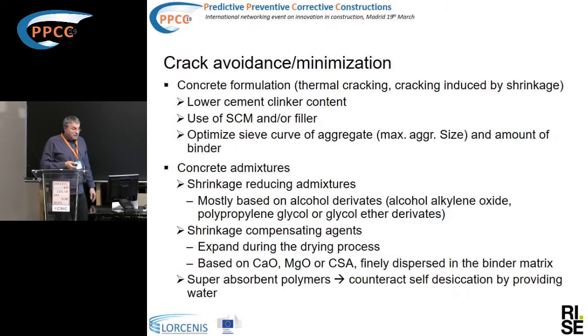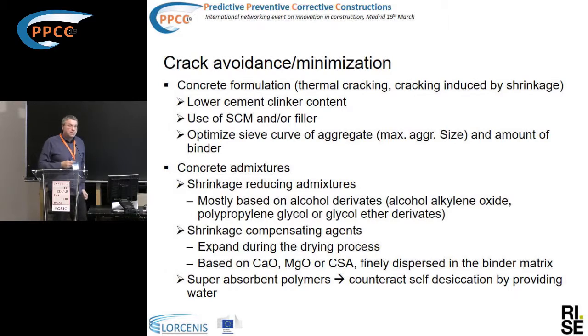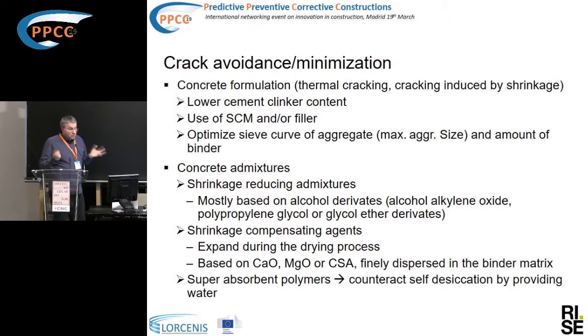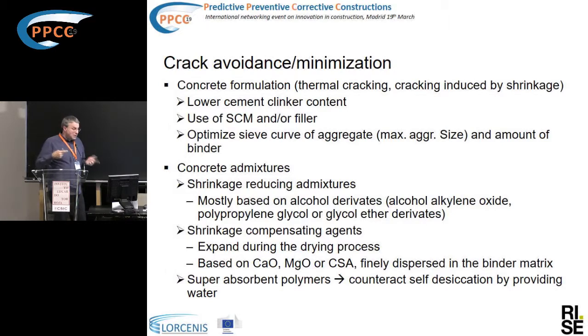There also exist shrinkage-compensating agents, which are less well known and are usually based on expansive minerals, finely dispersed and mixed into the concrete, acting in parallel during the shrinkage process to compensate it. Over the last 10 years another type of smart admixture has emerged — super-absorbent polymers — mixed into the concrete to counter self-desiccation by providing internal water, also effective to a degree for drying shrinkage. However, it is still difficult on an industrial scale to dose super-absorbent polymers in a way that has a reliable effect.